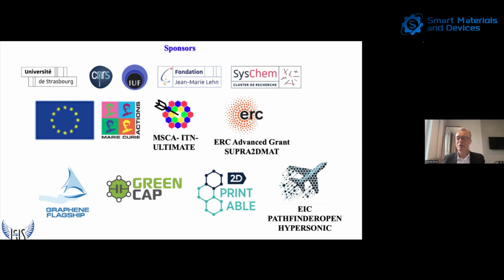Is it just complementary? Is it competitive technology? Well, we do also that, and I think they are complementary. For example, we interface MOFs and COFs with two-dimensional materials to make superlattices. We had a couple of papers in that direction. This approach is amazing because you can really tune the functionality bottom-up, so for a number of properties, that's the best tool. Of course, it's more complicated from his side to make perfect, large, and robust nanosheets. It's a big challenge also from the processing point of view. But I think the two things are highly complementary, and they must be used in a concerted manner, for sure.